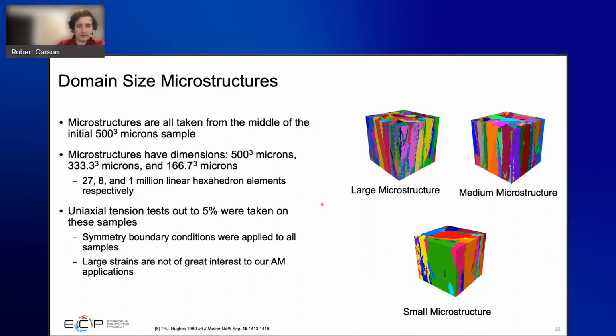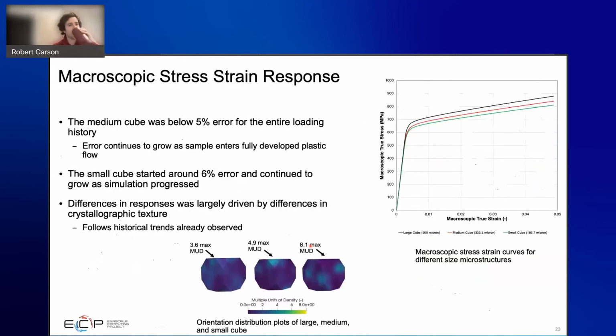In the first set of simulations that we ran, we only took things out to 5% strain, because within our projects we're not really concerned with large strains. We're really looking at the elastoplastic transition region in our material, so we don't have to go out to large strains to examine that. When we did that, what we found was this medium cube was below 5% error for the entire loading history.